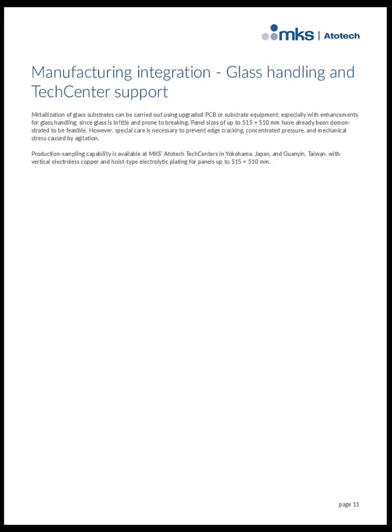Integrating glass substrates into manufacturing requires specialized handling due to their brittleness. Panels up to 515 by 510 millimeters have been demonstrated, but care must be taken to avoid edge cracking and mechanical stress during processing. MKS Atotech supports this integration with tech centers in Yokohama and Guanyin, equipped for vertical electroless copper and hoist-type electrolytic plating on large panels. This production sampling capability helps customers validate processes and ensure smooth manufacturing transitions.